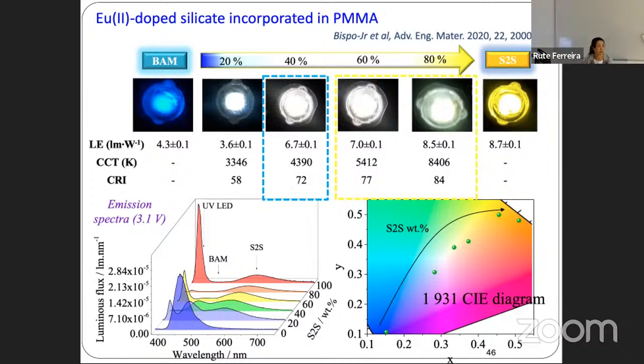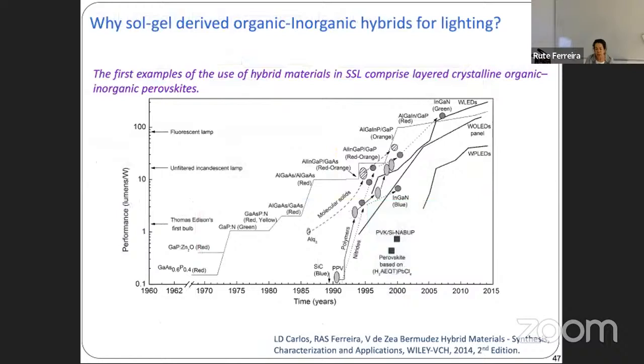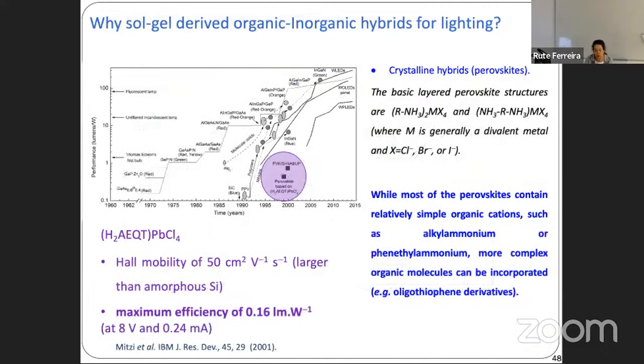Okay, this is one class of materials that were typically incorporated into polymers, but I also want to address today sol-gel derived organic and inorganic hybrids. And why? In fact, the first examples of the use of hybrid materials in solid state lighting comprise layered crystalline organic and inorganic perovskites. At the time, it was reported a maximum efficiency of 0.16 lumens per watt, a value one order of magnitude lower than what I just reported before.